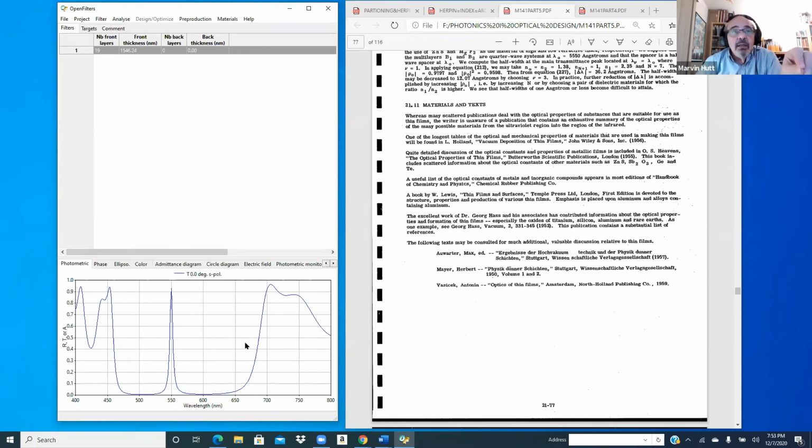It is a metal dielectric filter, which has the transmission properties of passing like a big broad thing like so, which we would center on this, and it would eliminate the red portion of the spectrum. That's called the blocking. So an interference filter, which you're going to be using for your selective experiments, has a double specification all the time.